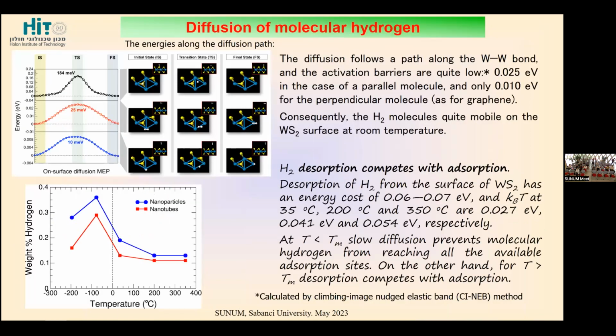Another one is diffusion of molecular hydrogen from one location to another. This is more related to our measurements at low temperatures, because diffusion is quite favored by high temperatures, but adsorption is favored by low temperatures. So we always have this type of competition. We calculated the diffusion barriers, and these diffusion barriers are very low, in the range of kT of the Boltzmann distribution. At very low temperature, the adsorption is quite favorable, but diffusion is very slow. At high temperature, the adsorption is not so favorable, but the diffusion is high, and at some intermediate temperature, we have some optimal point. Here are the graphs and the diffusion path as calculated.